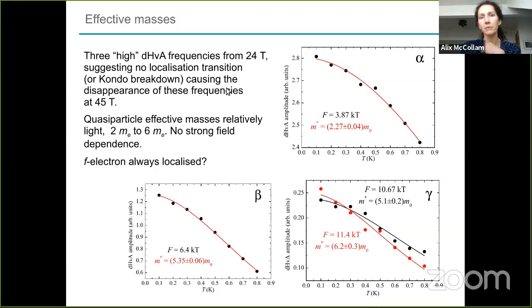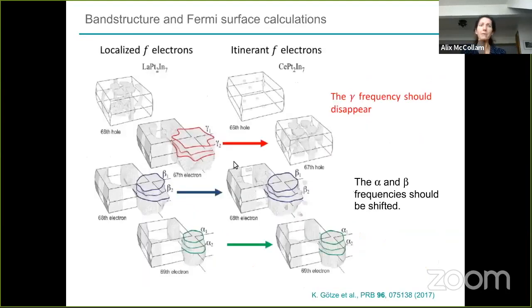The fact that we see these frequencies, and for their mass there's very little field dependence, nothing really changes going across this region at 45 Tesla. So from 24 Tesla all the way up to the highest field that we measured, which I'll show you in a moment, was actually 70 Tesla because we did the measurements in pulsed field as well. We see no change in the Fermi surface, at least in the dominant branches that we're able to observe via the de Haas-van Alphen effect, and not really any change in the effective masses either. So this indicates actually that the f-electron is localized all the way from 24 Tesla up to the highest magnetic field. More evidence is if we compare with the band structure calculations.